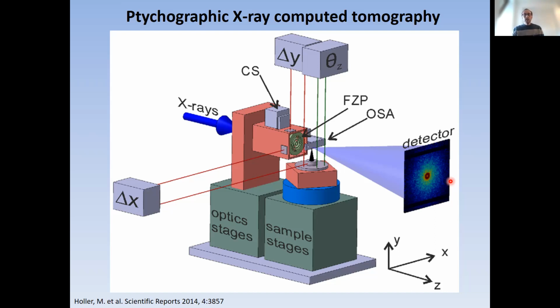And it has two advantages over X-ray tomography, which I think makes this technique really exciting and really useful. One is that the resolution is better. So we can get resolution in the order of 50 nanometers, sometimes a bit better than that. And the second is that it's quantitative. So we get an electron density map that we can directly correlate to the composition of the material.